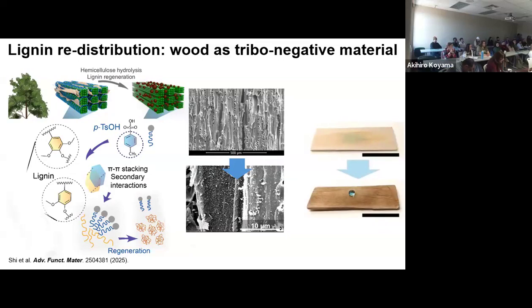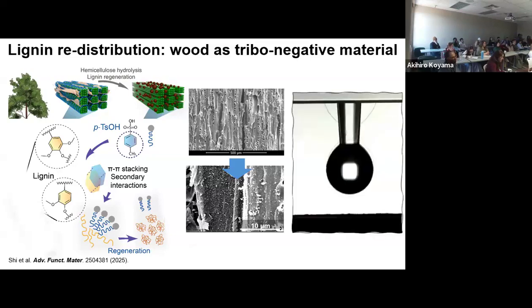And by doing that, you notice we go from something that is more or less light to something that is darker because the lignin goes to the surface. But also here you put a droplet of water and it will spread, completely wet. Here it doesn't wet. That in itself is enough to say, okay, this is a very nice way to engineer wood to make it super hydrophobic. But the student, now a postdoc, went a step further.